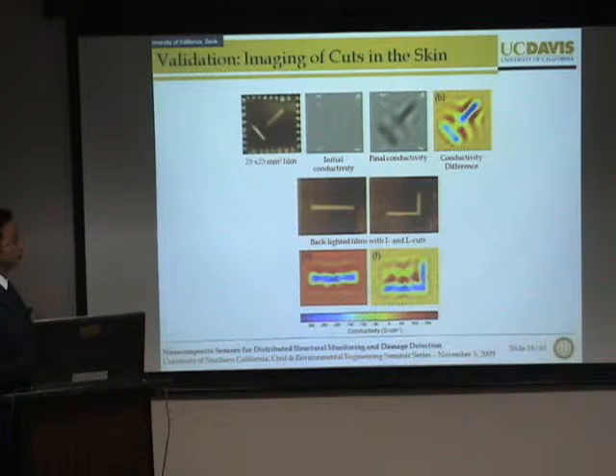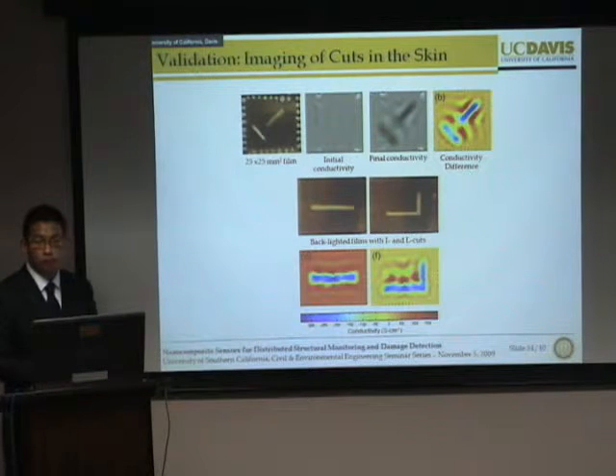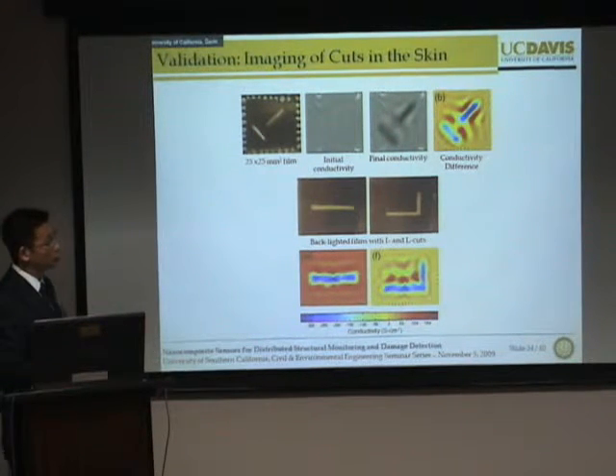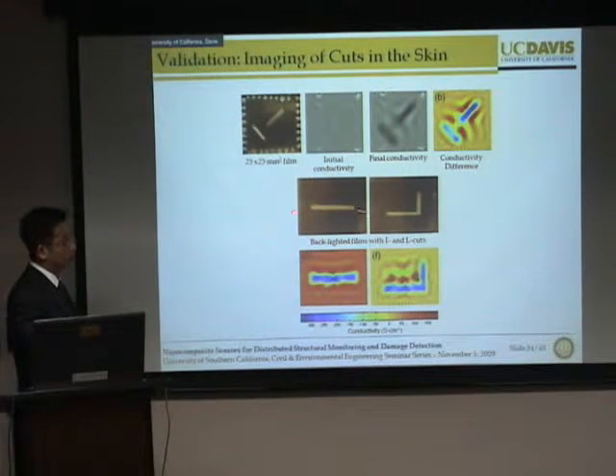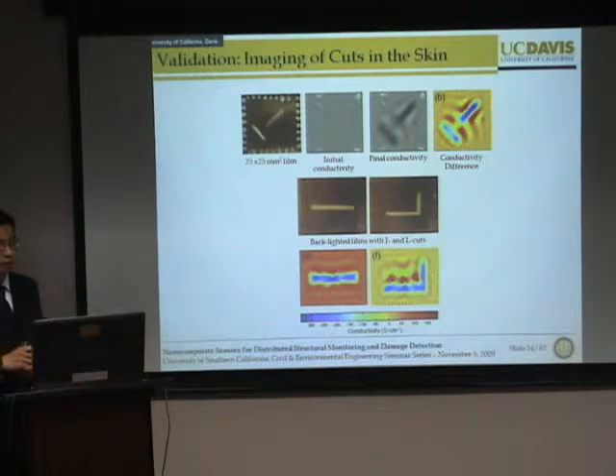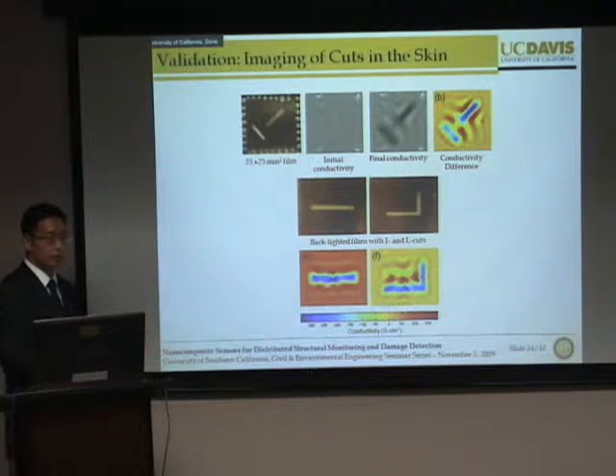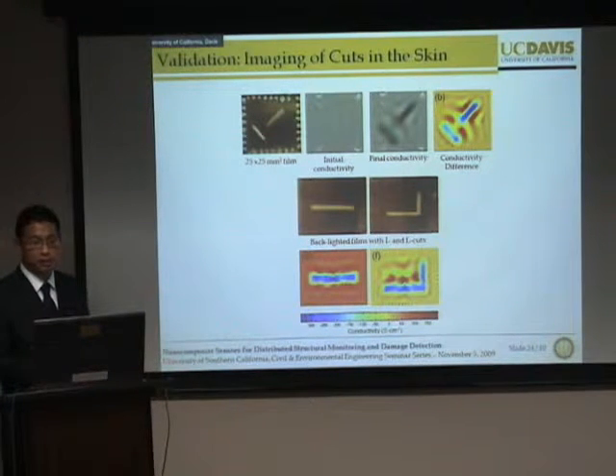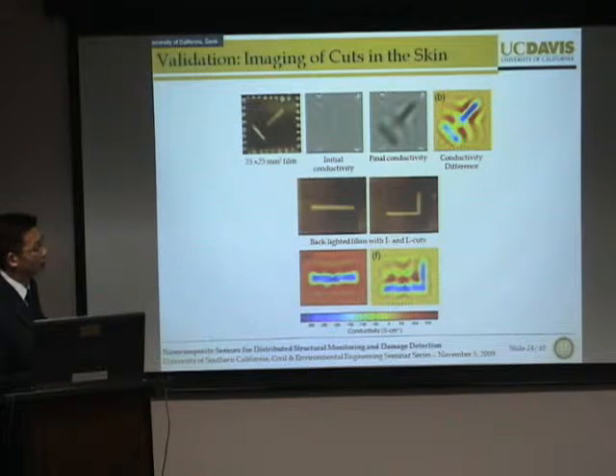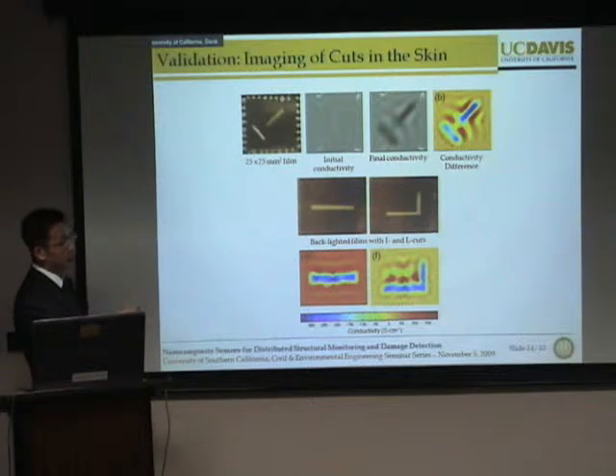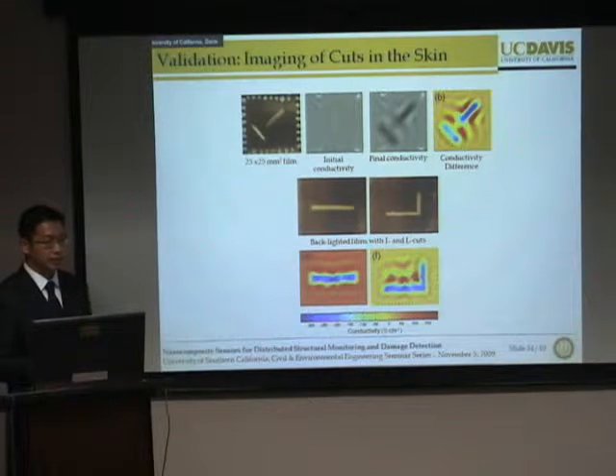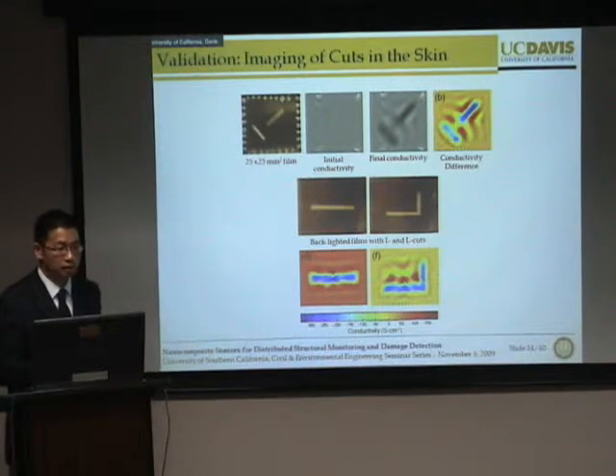So to validate this technique, we fabricated a plethora of different types of films. We can run the EIT algorithm to obtain some initial conductivity distribution. But what's more interesting is we can actually mechanically etch out different patterns on the surface of this thin film to create regions of zero conductivity, where we can then run the EIT algorithm again to determine and estimate its spatial conductivity and compare that to its original baseline conductivity map. And what you can see is that the conductivity difference for these different thin films correspond to the experimental pictures that we've taken, thereby validating that this technique has some promise to detect changes in conductivity.